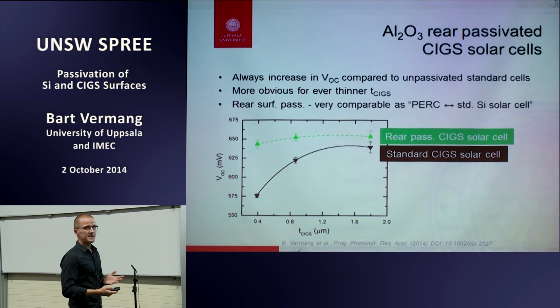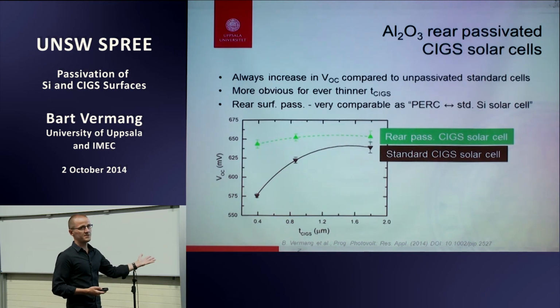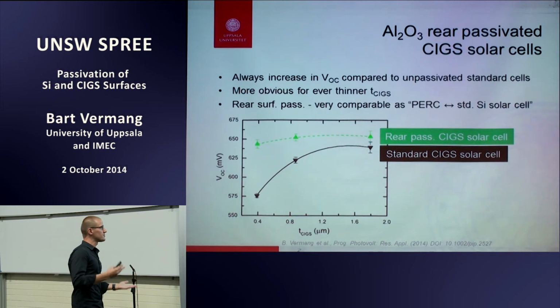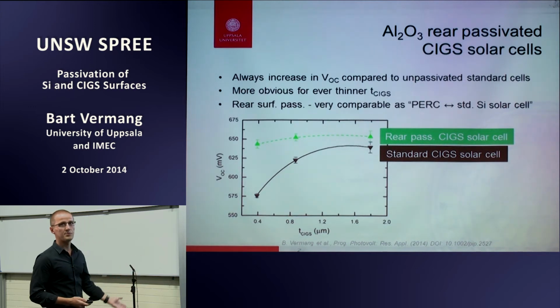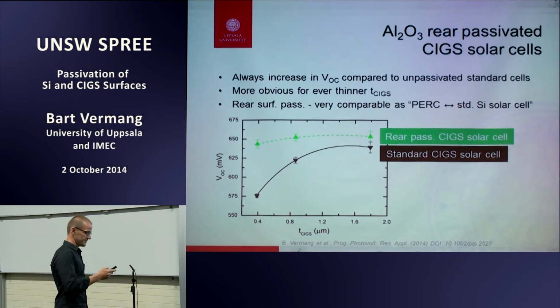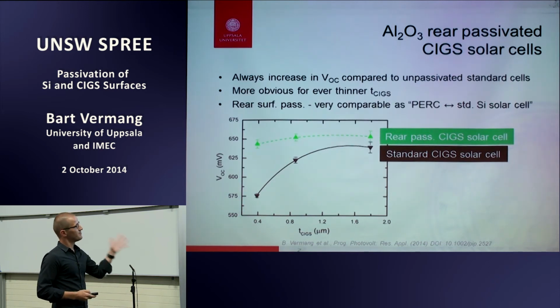You see an increase, or at least you can keep the same VOC for having a thick absorber layer as having a thin absorber layer by having a passivation layer, which is not the case if you have a standard cell without a passivation layer, because you bring this highly recombinative rear interface closer and closer to the space charge region, so you just lose a lot of electrons. You have a lot of recombination at the rear interface. So here, this is very parallel to what we have seen in silicon already for several decades.